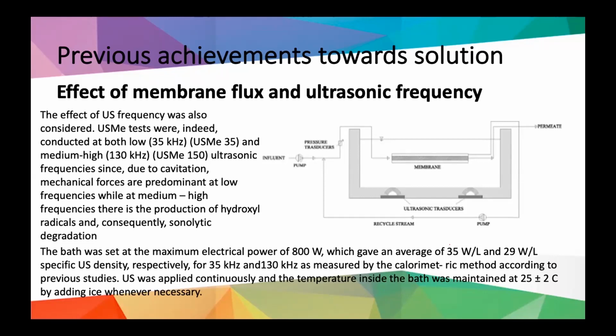If we highlight this technology, as you can see in the drawing in front of you, we have a bath containing 2 ultrasonic transducers, which give an ultrasonic frequency with a variable frequency. We have tried in this work 2 frequencies, 35 kilohertz and 130 kilohertz. 35 denotes the low, and 130 denotes the medium-high ultrasonic frequency. The maximum electric power was found in the bath where the membrane was treated with this ultrasound.